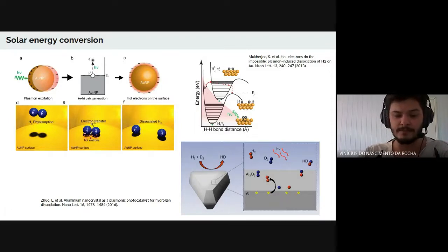DFT has trouble treating excitations and charge transfers. By contrast, embedded correlated wave function theory contains the right physics to do so and has identified two distinct mechanisms for hydrogen dissociation catalysis. Charge transfer excited states with reduced barriers facilitate hydrogen dissociation on gold, whereas resonant energy transfer enables photocatalysis on aluminum.